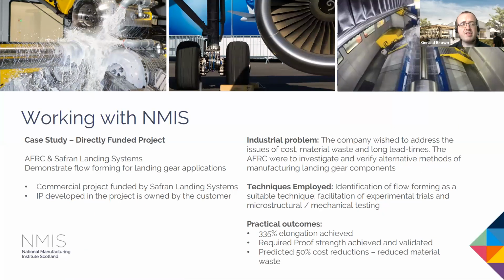And we predicted 50% cost reduction, mostly due to reduced material usage. It's important to highlight here as well that the benefit of being able to elongate the part as much as we did from the starting preform is that although there may be machining required on the preform, we were able to extract multiple parts from one single length or formed length. That stops you from taking 3 starting billets and having to core out each individual billet. So there is also potentially a good process time saving there as well.